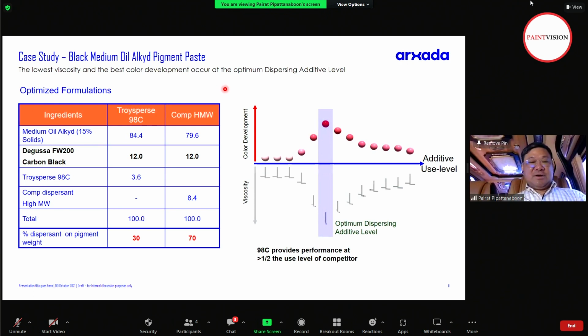We just give you a study with the Degussa FW200 carbon black. All right. This is a very high jetness, high surface area type carbon black. We do 12% pigment loading in the medium oil alkyd. And the dispersant that the customer is using as an incumbent today is a high molecular weight carboxylate type block copolymer. So they use about 70% on pigment weight, and 98C uses only about 30% on pigment weight. Both of them are different chemistry. All right. Fatty amine derivative with 98C, roughly 95% and more active. Competitive high molecular weight is a block copolymer type, which has about 40% active.